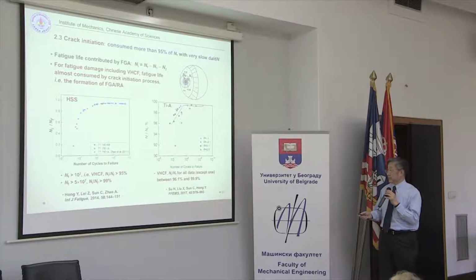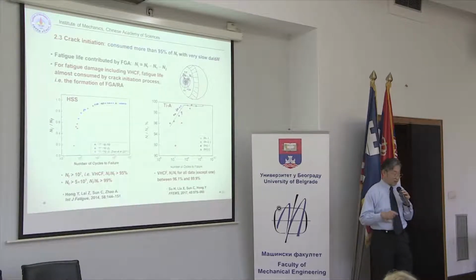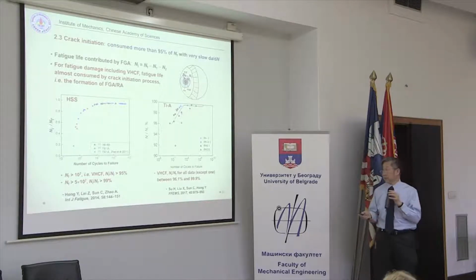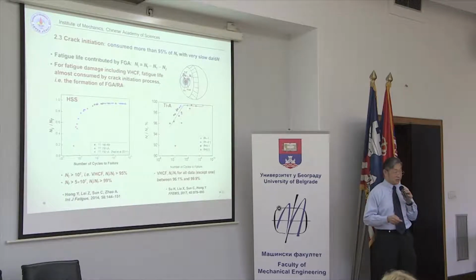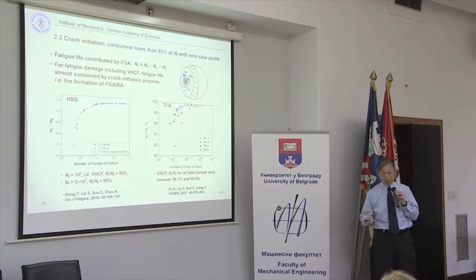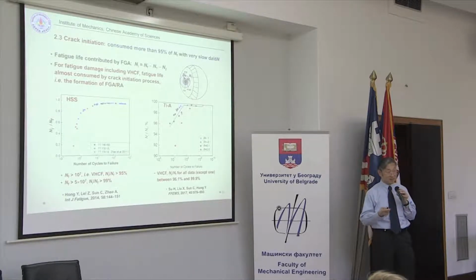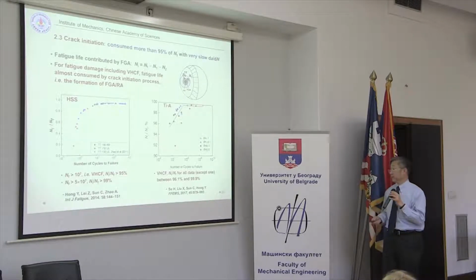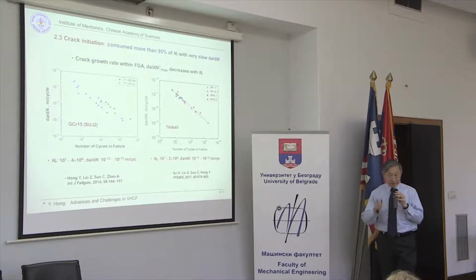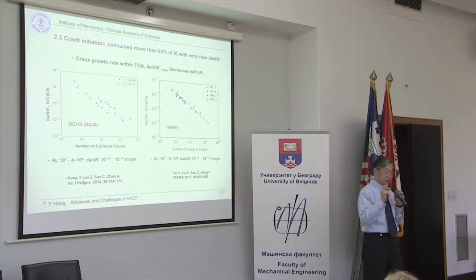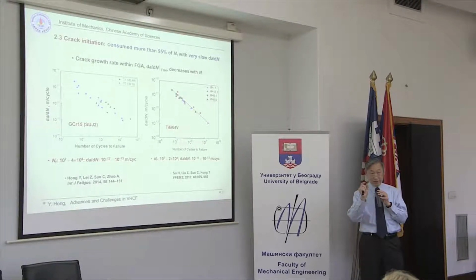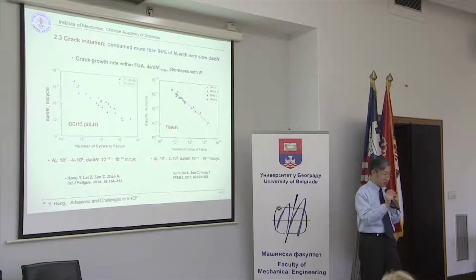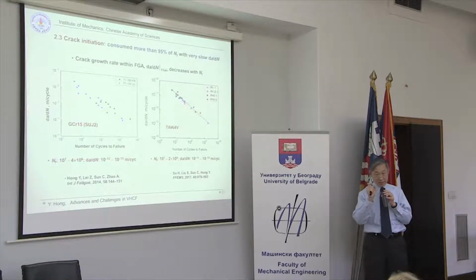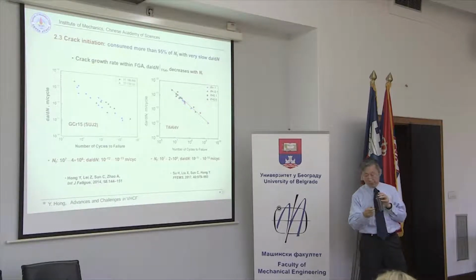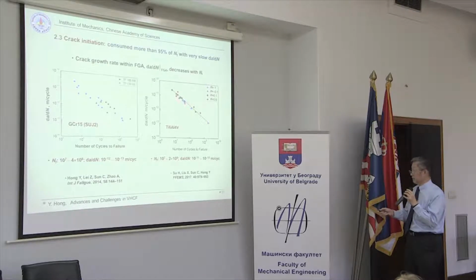So I just reiterate that for fatigue damage containing Very High Cycle fatigue, the majority of fatigue life is consumed by the initiation phase, the initiation process. So it's a very, very important phenomenon for Very High Cycle fatigue. It's quite dangerous for engineering structures. And if we know the life consumed by initiation, and also the size of this initiation area, we can get an average crack growth rate or crack extension rate. So it's simple.